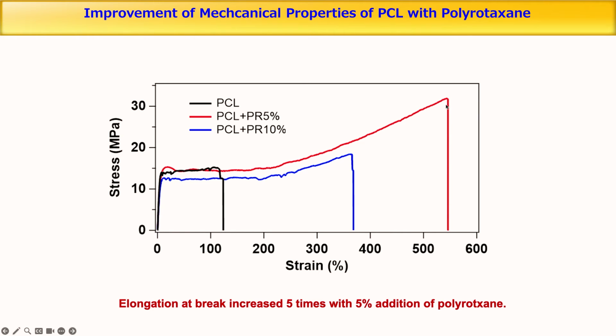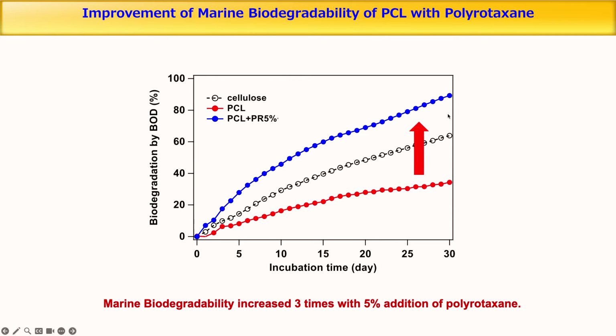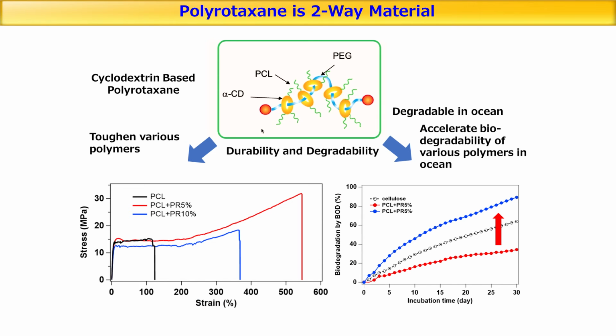It becomes very strong. It does not just become stronger, but also more degradable, as shown by the number of days and the level of biodegradation by BOD vertically. The white circle represents cellulose, which is used as a standard material. Polycaprolactone, in fact, is a polymer that degrades less than cellulose. But if you add this necklace, its degradability is enhanced and accelerated degradation occurs. Therefore, with polyrotaxane, these necklace supermolecules can make the material both stronger and more degradable. Achieving both these characteristics is possible.